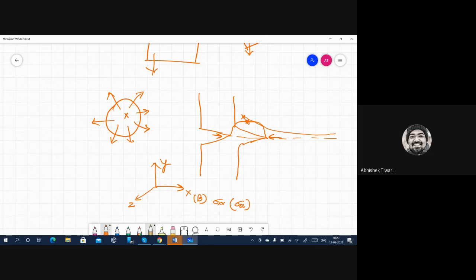So these two profiles would cause different amounts of constraint, although this is a single thing. The constraint is a single thing, but you can divide it into two effects. One effect which is coming from the thickness direction, one effect which is coming from the ligament direction.